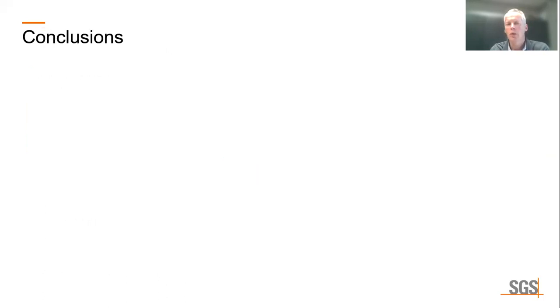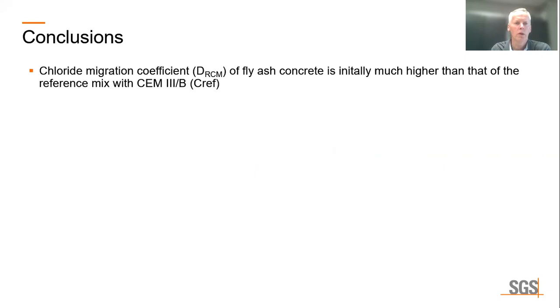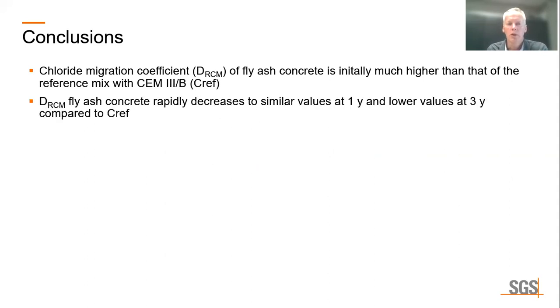So now I come to the conclusions of my presentation. First, the chloride migration coefficient of fly ash concrete is initially much higher than that of the reference mix with blast furnace slag cement, but the fly ash concrete shows a very rapid decrease to similar values at 1 year and lower values at 3 years.